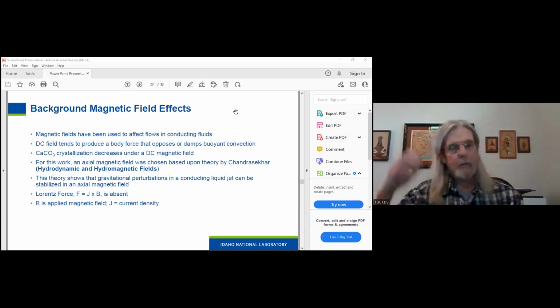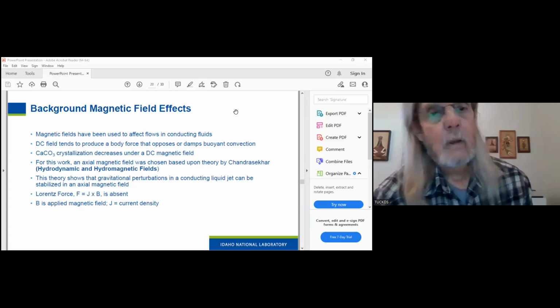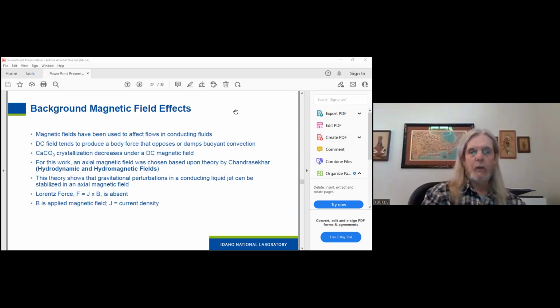Now, magnetic field effects. Magnetic fields have been used to affect flows in conducting fluids. DC field tends to produce a body force that opposes or damps buoyant convection. For example, calcium carbonate crystallization decreases under a DC magnetic field. For the work I did, I used an axial magnetic field, and that was based on a theory by Chandrasekhar in his book, Hydrodynamic and Hydromagnetic Fields. This theory shows that the gravitational perturbations in a conducting liquid jet can be stabilized in an axial magnetic field. In this case, the Lorentz force is absent. Here, B is the applied magnetic field and J is the current density.